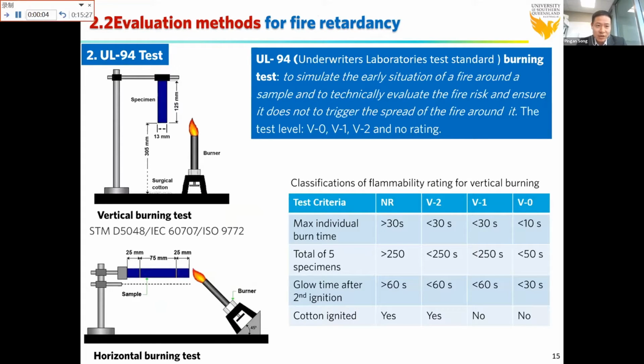The second method is the UL94 test. UL94 stands for Underwriters Laboratories standard burning test. It basically has two modes: the vertical burning test or the horizontal burning test. In industry, we normally prefer to use the vertical burning test, because it can simulate the early situation of fire around the sample and technically evaluate the fire risk and ensure it doesn't trigger the spread of the fire around it.